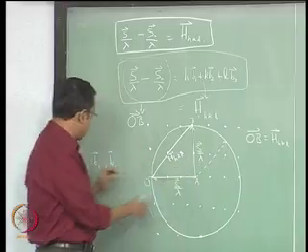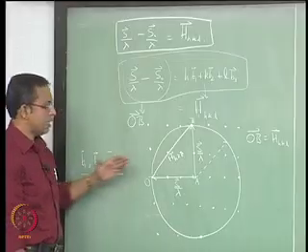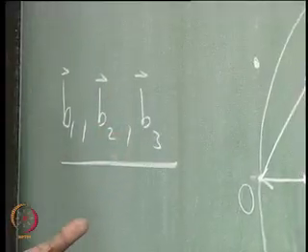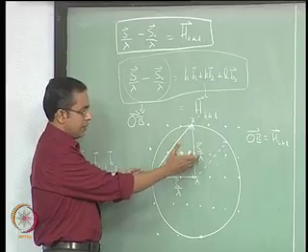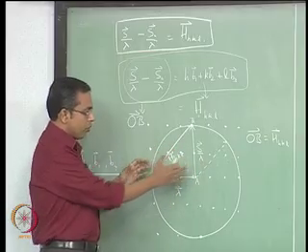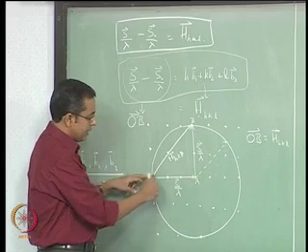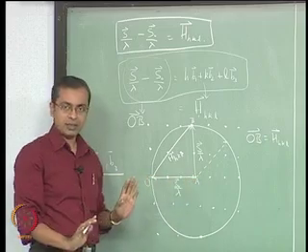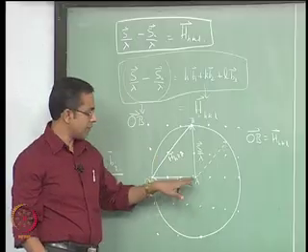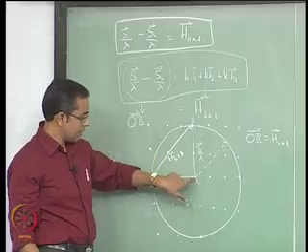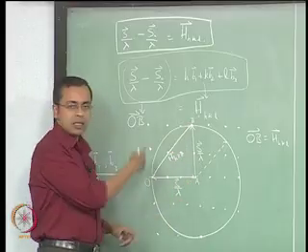So in fact, when you see here we have a B1, B2 and B3. So actually this information can also be drawn in 3 dimensions. When you draw it in 3 dimensions, what you see as a circle in 2 dimensions is actually a sphere in 3 dimensions, because this vector OA is fixed, and this vector OB can go in all directions around it, starting from the vector AB with A as a center. This B can go in any direction around it.